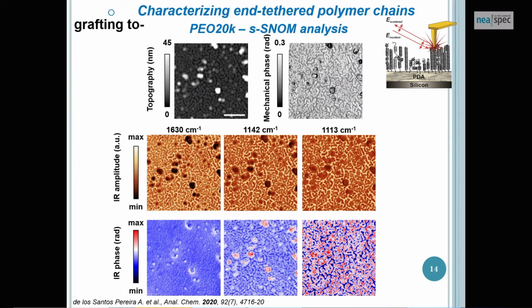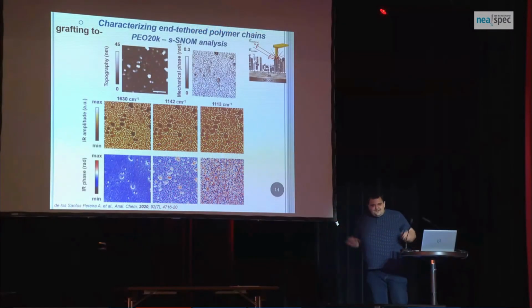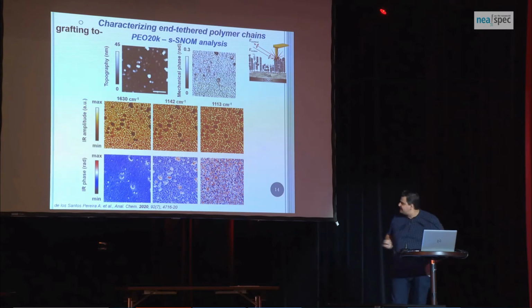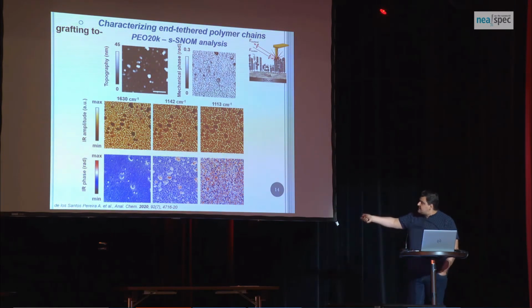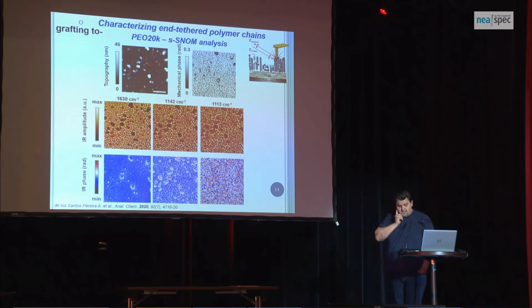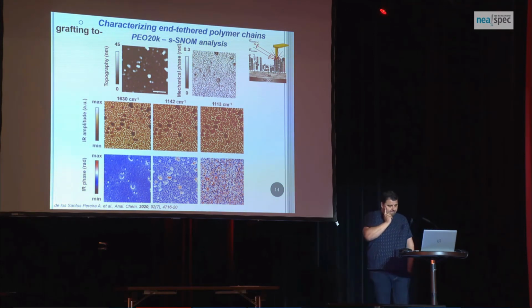Adrian was coming with a broad smile and was telling me, Ognen, your brush has holes. See how it looks like. And it's consistent, you know. This is the signature of the strongest vibration on the PEO chain. This is a shoulder in the far field spectra, and this is just something coming from the anchoring layer.